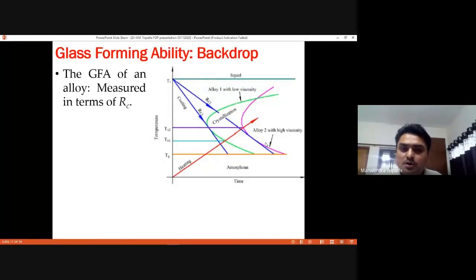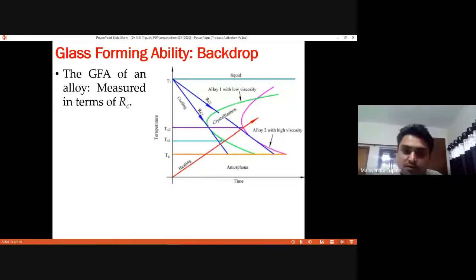And this is the cooling rate, meaning delta T, the change in temperature divided by delta time. So that is the cooling rate, right? For this particular alloy, you need to cool it fast. A high cooling rate is required. But for this alloy, even if the cooling rate is low, here it will be amorphous and here it will crystallize. Meaning if you are inside this nose, it will crystallize. So a higher cooling rate is required here. So this is not a good glass former. This is a better glass former than this. This is how we compare it.